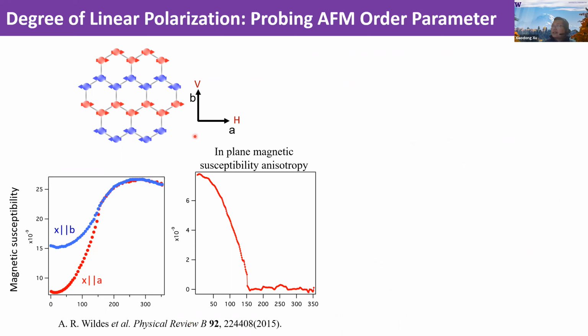The A axis is along the zigzag spin chain and the B axis is orthogonal. So you can see the in-plane susceptibility, along the A and the B axis, was initially equal to each other until below the Néel temperature, then they start to deviate.